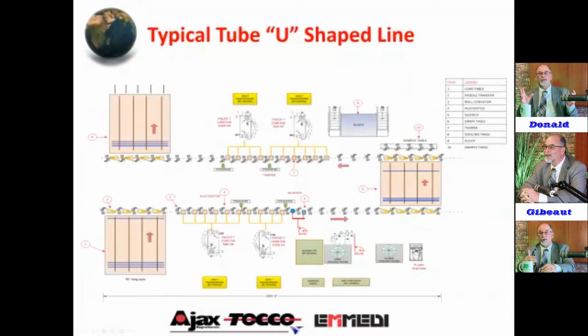Here's a typical, what we call a U-shaped line, where the product is coming down in the bottom here. Here's a set of paddles that it takes off, transfers over to the conveyor line, and then it goes through the austenitizer coils. And if you look at the power here, the Ajax Pacer T is a transistorized unit, IGBT, 2200 kilowatts at the 500 hertz. That 500 hertz then gauges that depth of penetration.